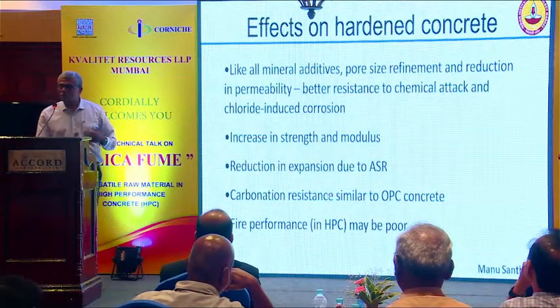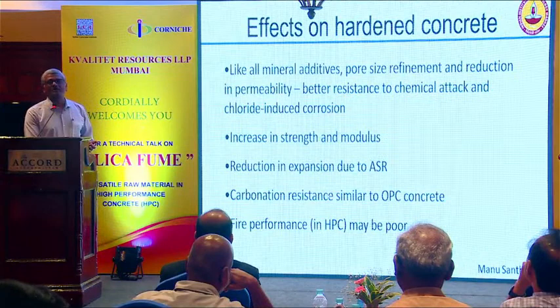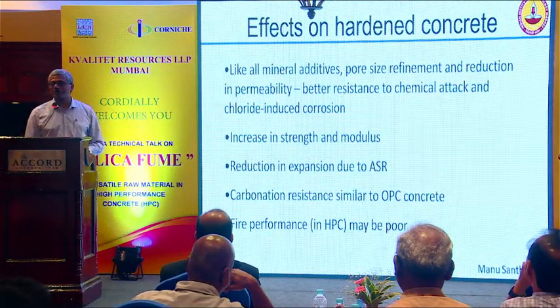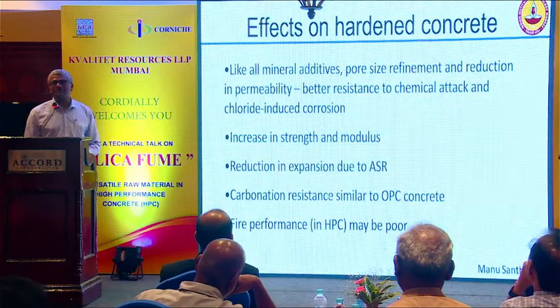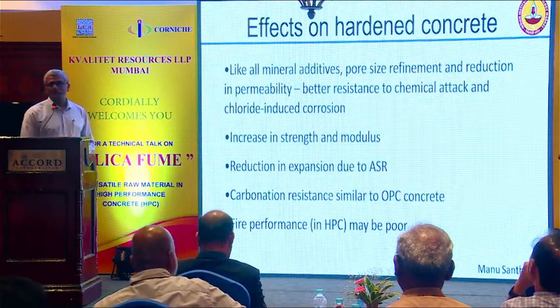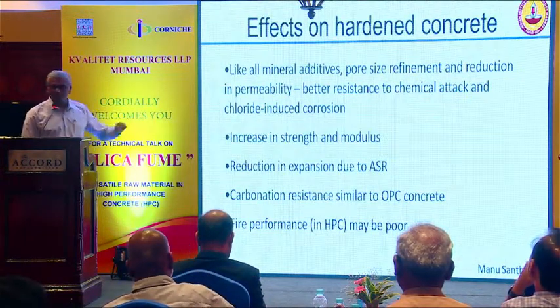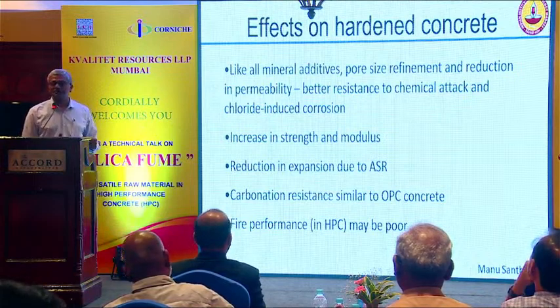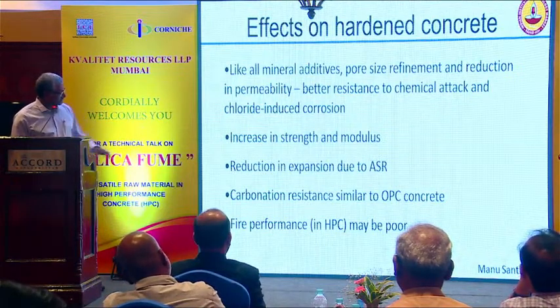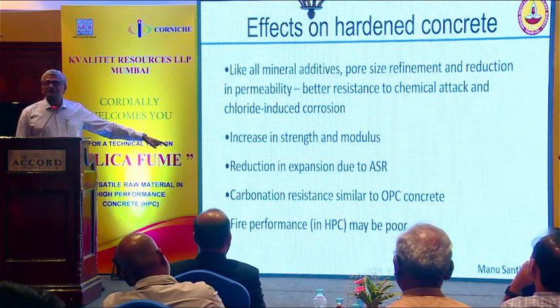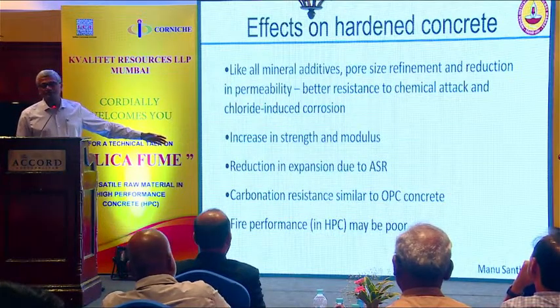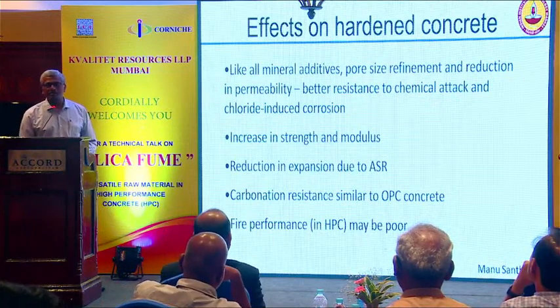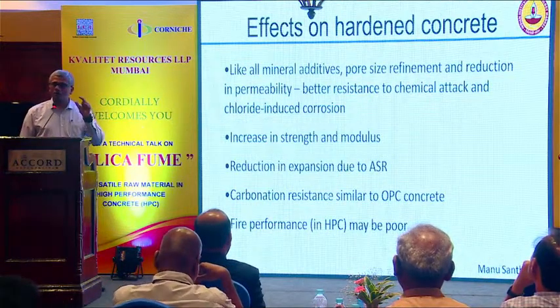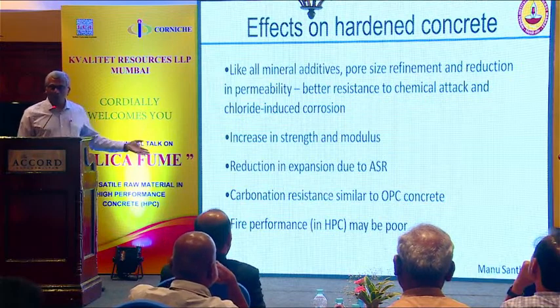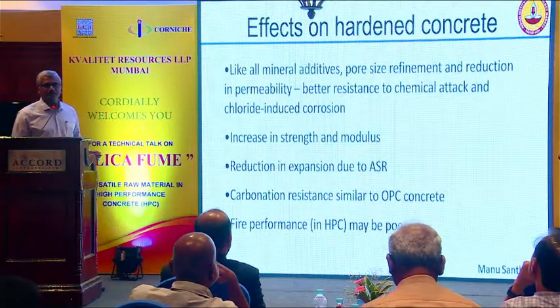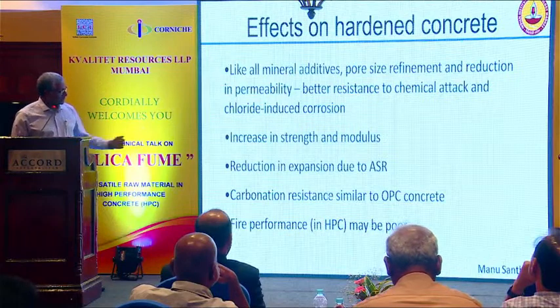Generally, strength also increases. For a simple replacement of cement, strength will also increase by 7 days, 14 days. One day you may not see that much of an increase, depends on the mix design, but you will definitely see an increase in strength. And the modulus. Your concrete will become stiffer with the increase in strength. In alkali silica reactivity, silica fume can really do very well. But of course, that's also true of all mineral admixtures. Whenever your aggregate is not of good quality, if it's reactive, all mineral admixtures will help in reducing the extent of expansion. Carbonation resistance.